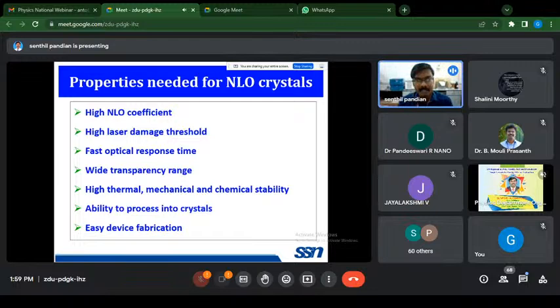So before we go for crystal growth, characterization or application, one has to ensure the physical and chemical properties of the grown crystal. It should have a high nonlinear optical coefficient. For laser application, one must know the laser damage threshold value of the grown crystal, so it should be high, with fast optical response time and a wide transparency range in the UV, visible and IR region, 200 to 1100 nanometers. For practical device application, one has to ensure the grown crystals have very high thermal stability. And if we go for cutting and polishing, one has to ensure the crystal is highly mechanically stable for practical device utility. So it should have high mechanical and chemical stability. The ability to process the crystal and fabricate the device should be very easy.